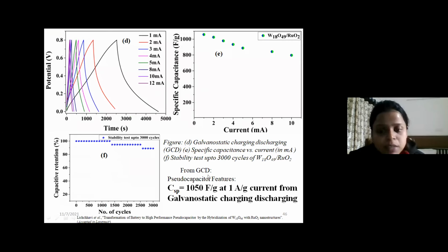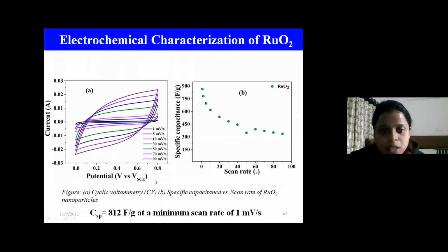So the mechanism behind this, okay, first the specific capacitance calculated from GCD is 1050 farad per gram at 1 ampere per gram, and we have done the stability test till 3000 cycles, and the material is giving a highly stable nature. Our purpose was to enhance the stability of the material, and it has been enhanced up to 92% stability over 3000 cycles. So there's a huge enhancement over 3000 cycles.